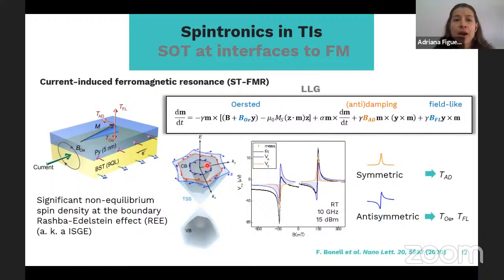This is a study about spin orbit torques at the interfaces of TIs with ferromagnetic materials. In this case, we used spin torque ferromagnetic resonance to study the spintronic properties, the spin orbit torques that are generated at the interface of the TI, in this case with a permalloy, which is a metallic ferromagnet. If you pass a current through your TI, there is a significant non-equilibrium spin density at the boundary of the TI as a consequence of the Rashba-Edelstein effect, that is also known as the inverse spin galvanic effect.